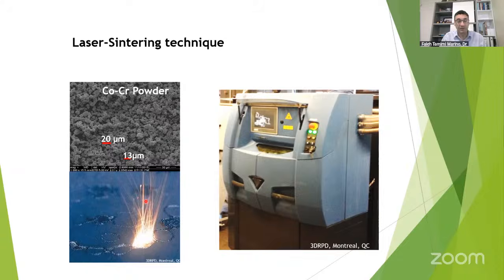So the laser can be operated through a computer, and so you can weld the particles in the right spots, okay? So here you can see an example. You see a layer of metal powder, and here is the laser beam hitting the powder, and by doing that it is welding the particles together. So in some areas, the particles are welded together, in other areas, the particles are loose.